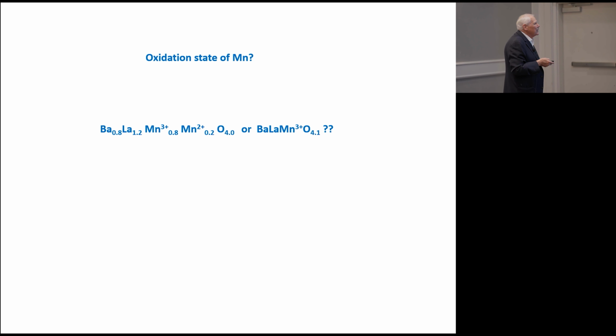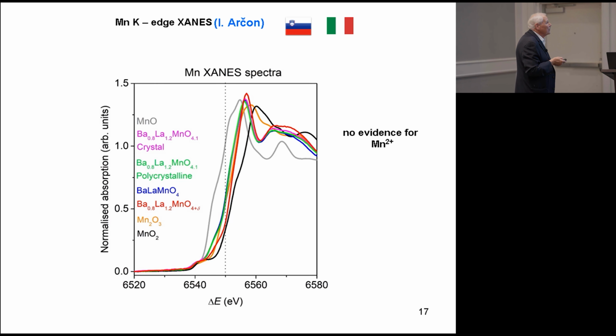Okay, so we're left with the problem of what on earth is the oxidation state of manganese? For example, again, we have this not 1-to-1 barium to lanthanum ratio, and so does it contain some manganese 2+ with 4 oxygens, or in fact, is it slightly oxidized, which would retain the old manganese 3+ oxidation state?